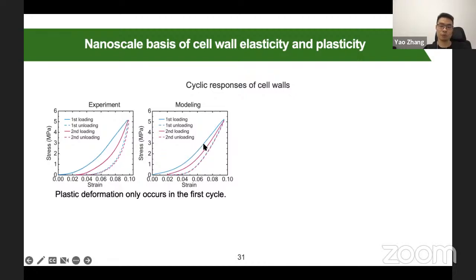And if we do the modeling, we find the same case. So basically, the plastic deformation only occurs in the first cycle. You can see that in the first cycle, when you do loading and unloading, there's a residual strain.